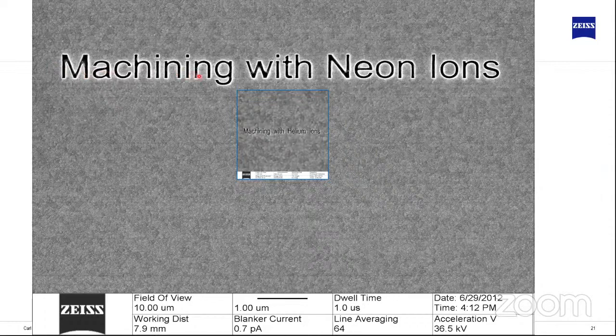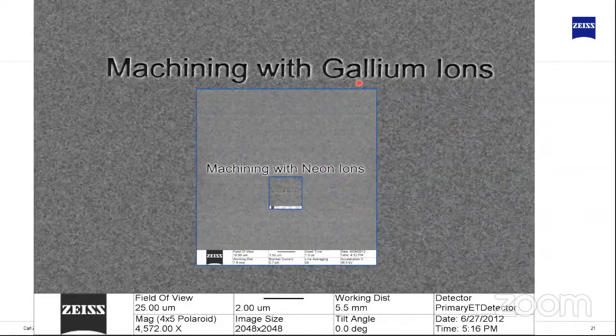We can nicely do that. And I told you we also have a gallium beam on the system as an option. So that means we can also use gallium ions. There we create structures in the range of, let's say, 100, 200 nanometers, something like that, if we are only writing into the surface. But what is very nice, what you can see here, is that for a certain feature size we have the dedicated ion. So we can do the rough milling with the gallium, intermediate stuff with neon, and the very fine stuff with helium. And if we compare the helium structure with the gallium structure, then we find we easily gain a factor of 10 in resolution if we want to go to very small structures.